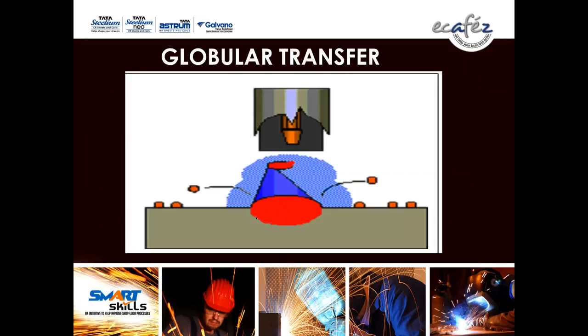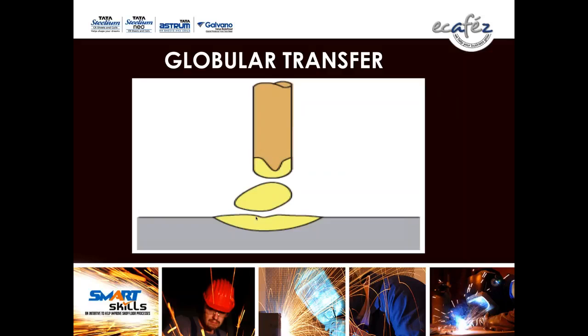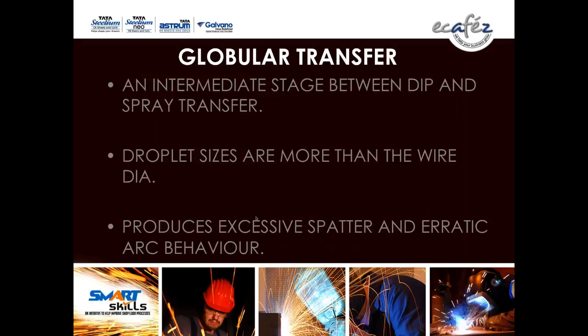Check the globular transfer. Always avoid this transfer. For the MIG process, go for dip transfer or spray transfer wherever possible. Don't go for globular transfer. For the quality of welding, you do not get a quality weld by using globular transfer. In globular transfer, 8 to 10% of weld metal will be lost. It has an erratic arc. This is a pictorial view of globular transfer. You never get a good quality weldment by using globular transfer. Globular transfer is an intermediate stage between dip transfer and spray transfer. Droplet sizes are more than the diameter of the electrode, producing excessive spatter and erratic arc behavior. You will not get good quality.